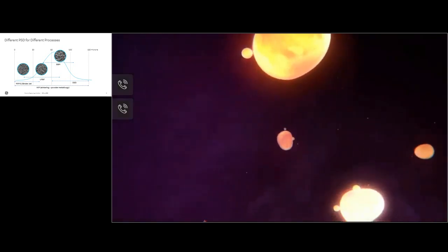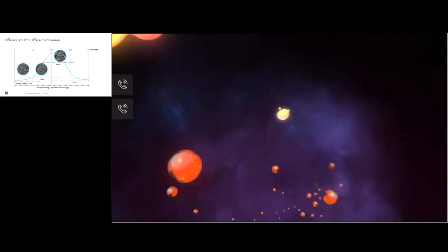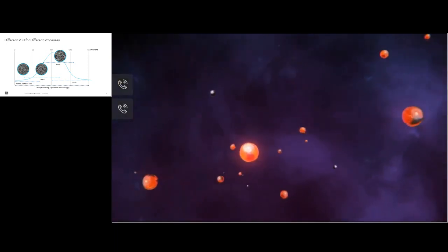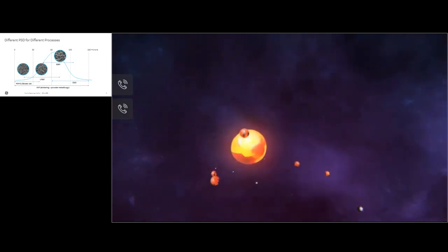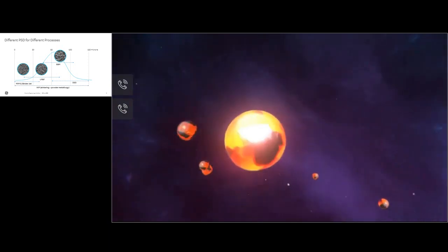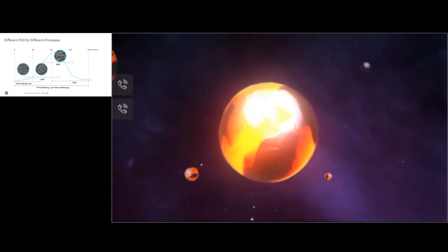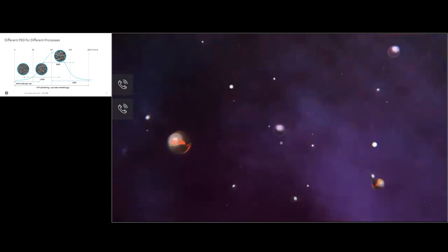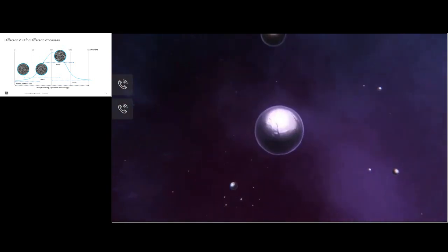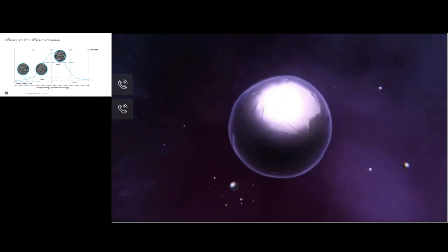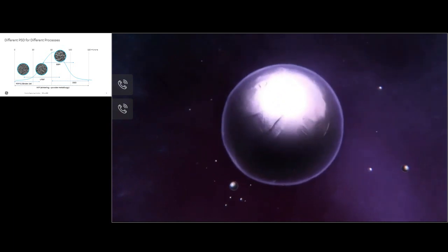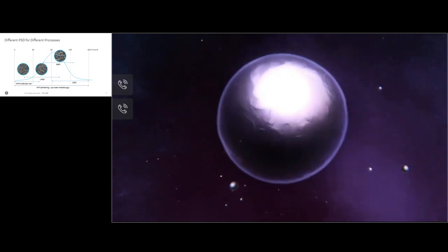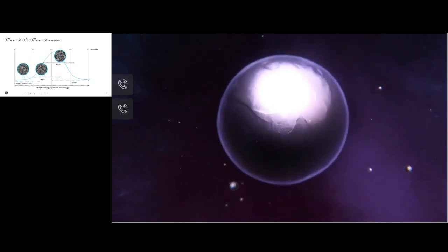The surface tension of the atomized particles reforms them into even spherical shapes. At the same time, residual argon gas is allowed to escape from the particle. This process avoids irregularly shaped particles and gas pockets that are typical with cold gas atomization. Fully formed particles typically range from 0 to 180 microns. They are highly spherical powders with superior flowability, low porosity and satellites, and feature device compatibility across all additive manufacturing modalities.